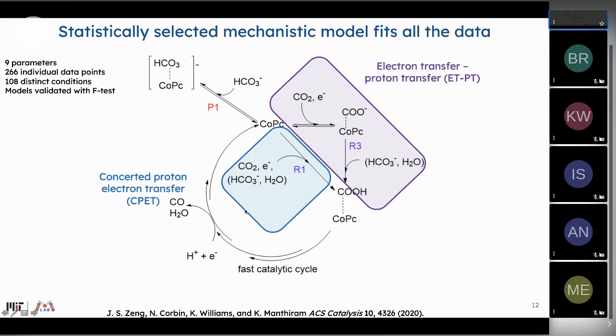We also see that bicarbonate poisoning is necessary. Mathematically, the system is allowed to choose whether or not bicarbonate poisoning is important. And the only way we can account for the data that we see is by having bicarbonate poisoning have relevant kinetic constants that in fact mean that bicarbonate poisoning is occurring.